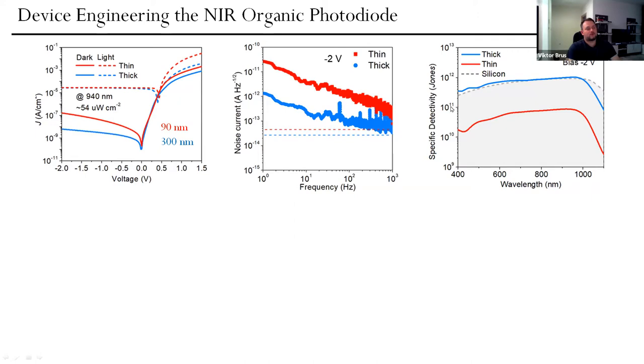And if we compare the specific detectivity, which shows the ratio of useful signal to the noise signal, we see that the thick device exhibited quite a higher specific detectivity, comparable to a silicon photodetector. So if we think about it, it's quite an achievement for a 300 nanometer plastic layer to compete with established silicon technology.